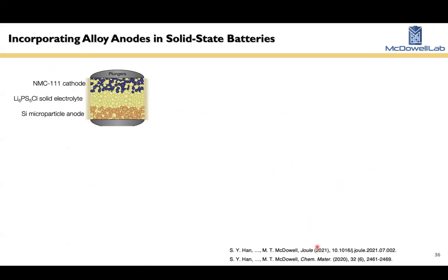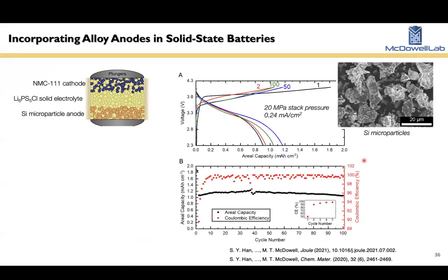Good. So, volume changes. These volume changes are associated with structural and mechanical degradation in these materials. So understanding and controlling this is really important in solid-state environments. One of the very interesting things about alloy anodes in solid-state batteries is that they have actually shown very good performance. This is from the same paper from my group, where we take silicon microparticles and make composite electrodes with sulfide-based solid electrolytes, and we cycle them in batteries, and we see decent cycling over 100 cycles, pretty good stability.